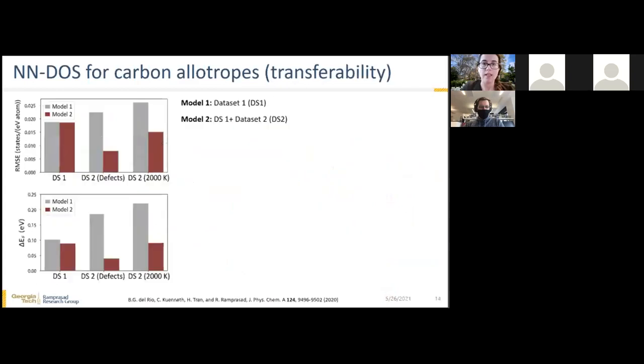And also then we have to test the transferability to new environments, which, as I already said at the beginning, is one issue with machine learning models in general. They will not perform that well in transferability tests, especially if the transferability is to completely new environments. So here, our data set, as you recall, was graphene with some defects, and also we included configurations, snapshots from molecular dynamics runs, but at 2000 Kelvin. So there was higher disorder, but it still was from C60 or the carbon nanotubes.